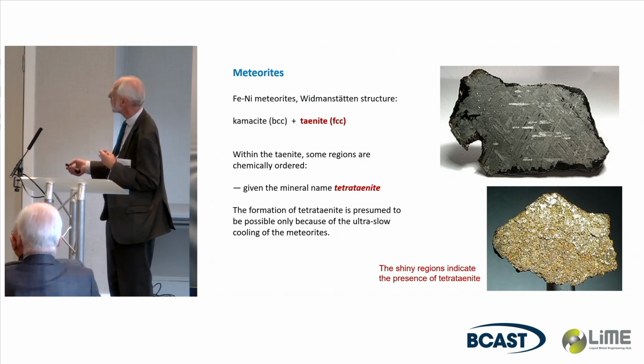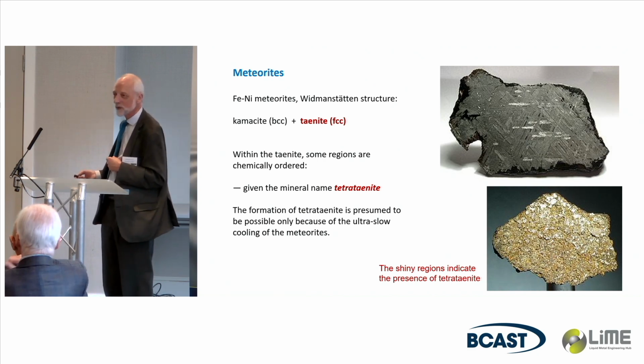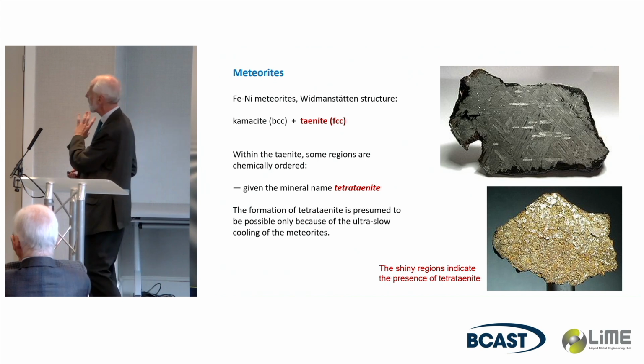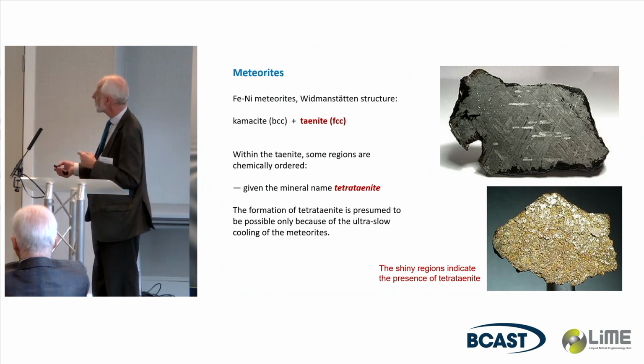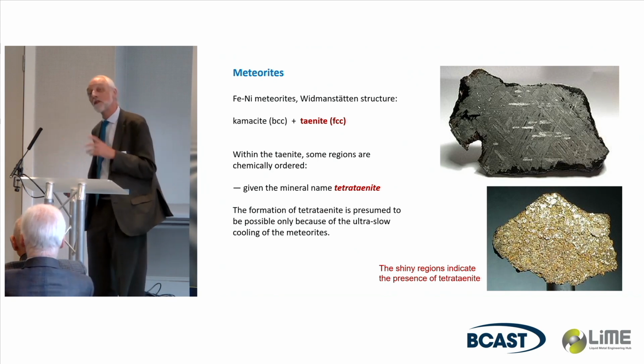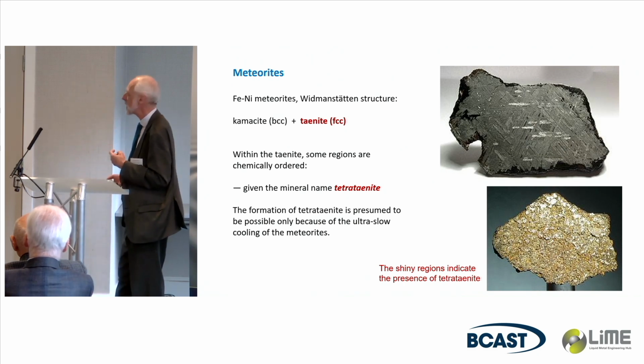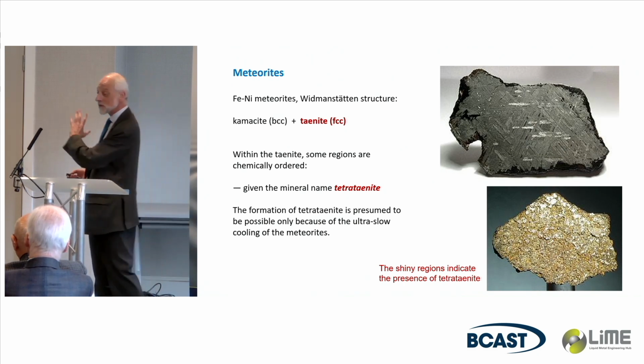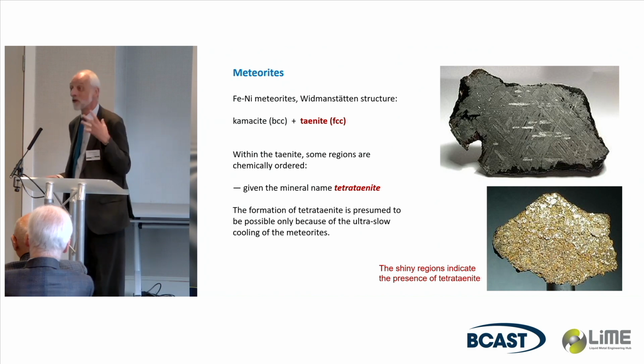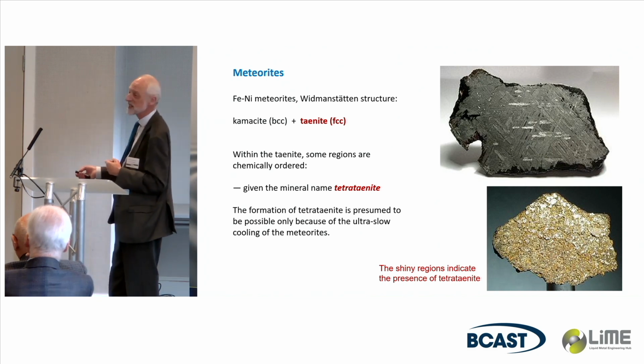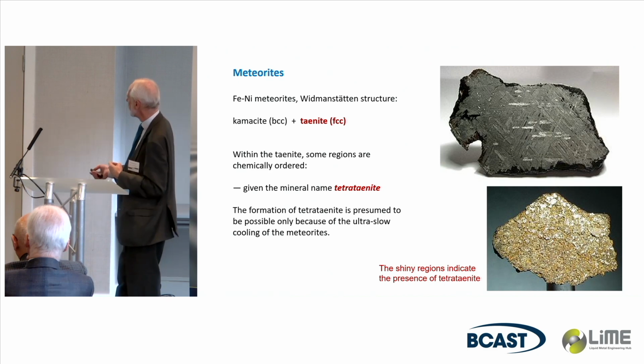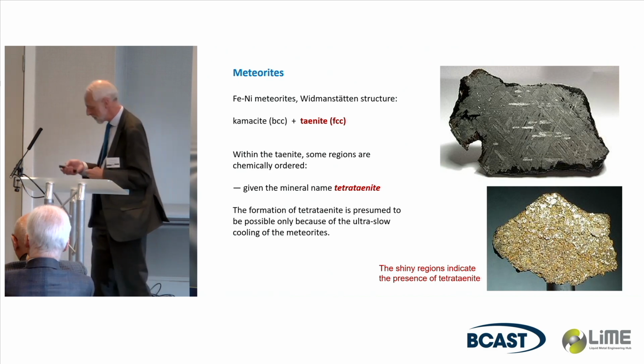And two phases, one of which is taenite, which is the face-centered cubic phase. What was discovered later was that some of that taenite was not cubic but tetragonal, and showed the ordering that I was talking about before. Because it was found in meteorites, it had to be given a mineral name, and they chose the name tetrataenite. And between cross polars, it shows up as nice and sparkly.